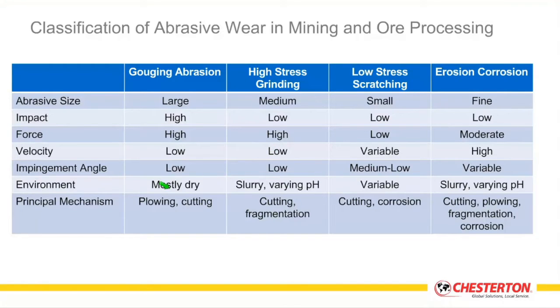If you're dealing with high stress grinding, it tends to be more of a cutting and fragmentation wear. When you get into low stress scratching, it's more cutting and corrosive wear. And when you get into erosion corrosion, it's similar to the low stress, but you also have to add in the plowing, fragmentation, and corrosion factors. So these are all properties that come into play as you start to impact the different types of coating situations that you might want to select.